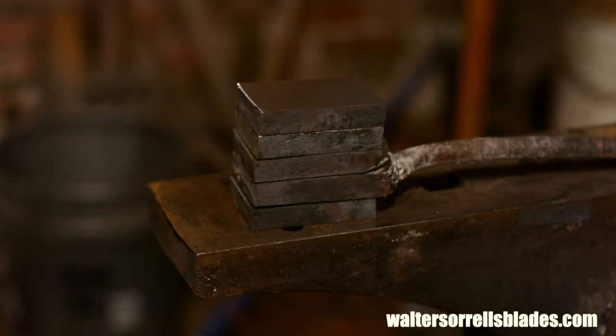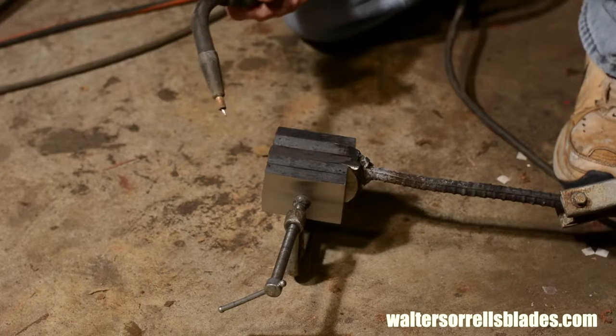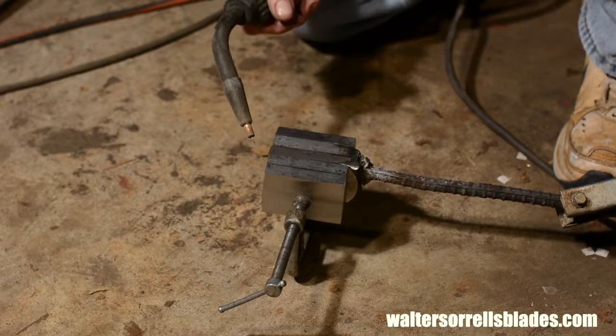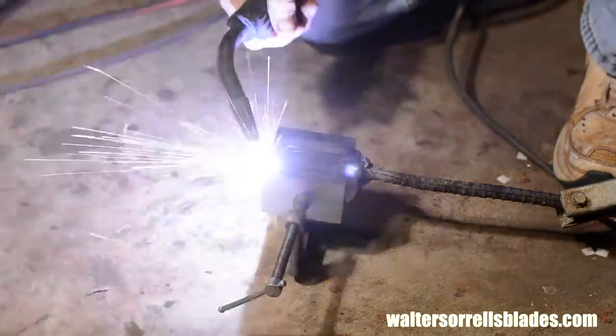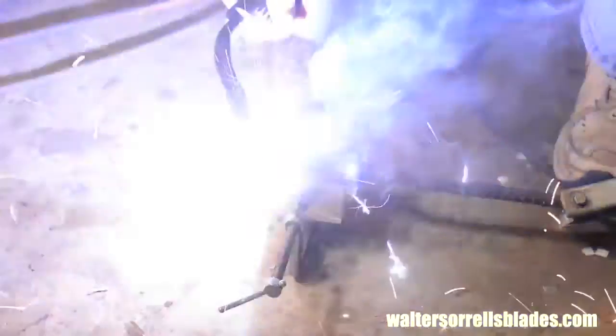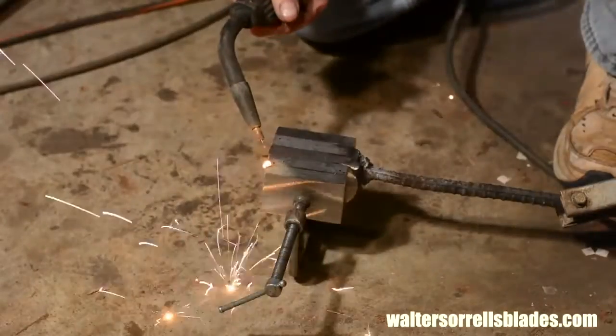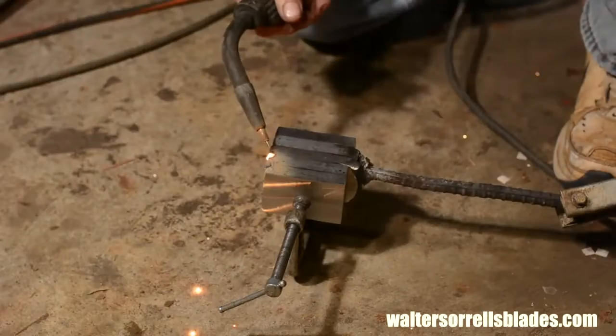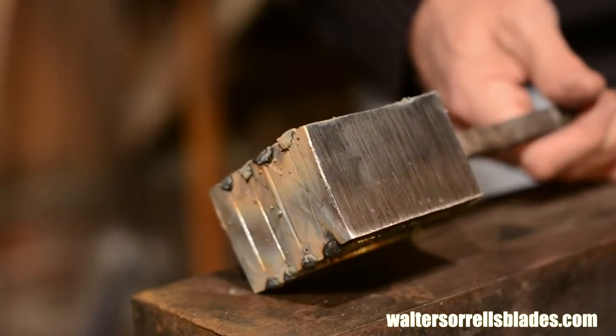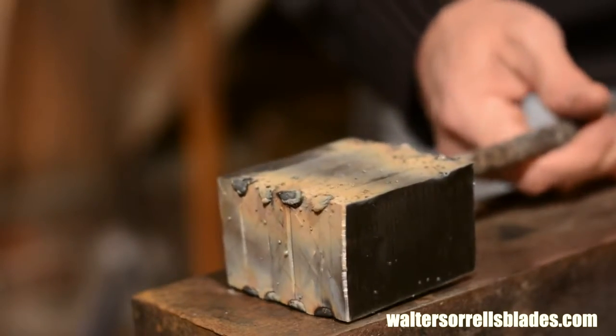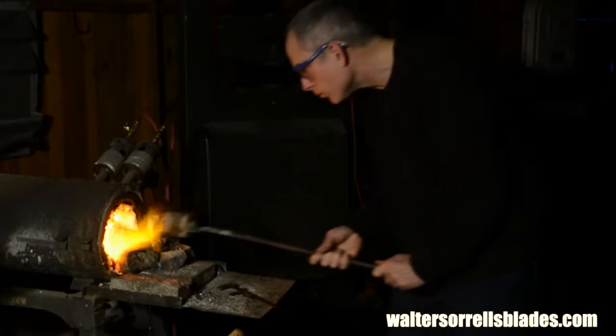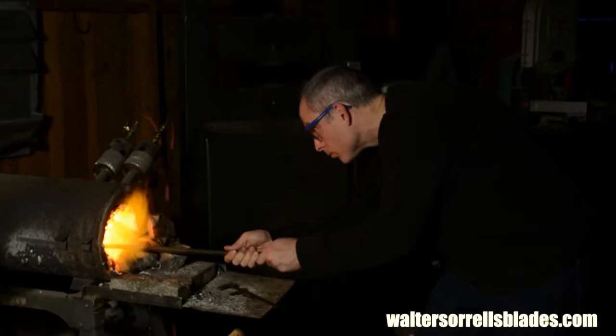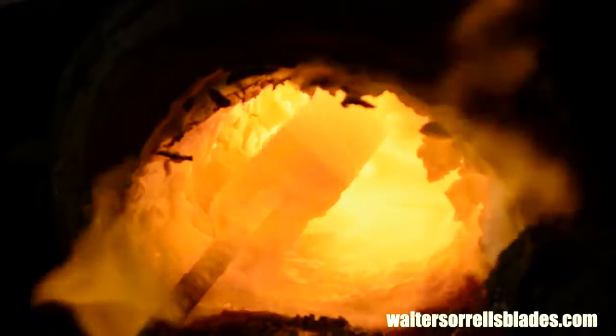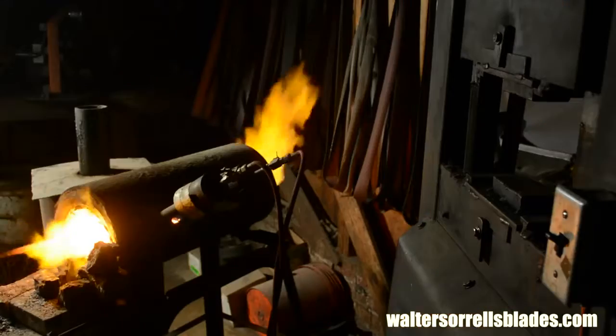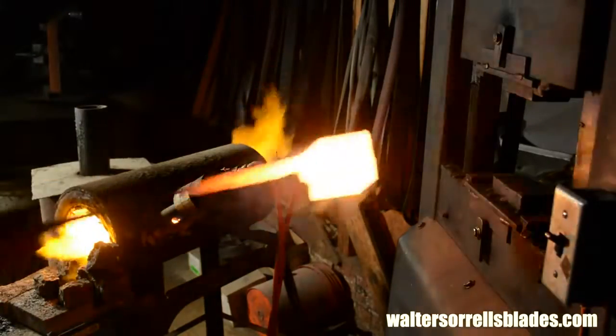Next, I'll stack up all 5 pieces that I've made and tack weld them together again just like I did the first ones. As before, I'm using the absolute minimum amount of weld material possible. Then fire up the gas and forge weld the stack exactly like you did the first one. Just repeat that stacking and welding however many times you need to reach your desired layer count.